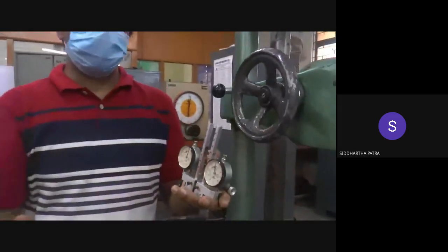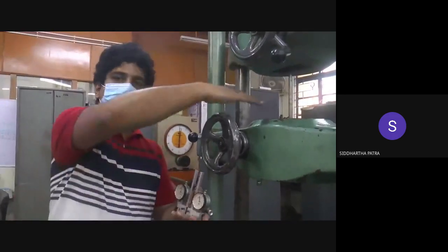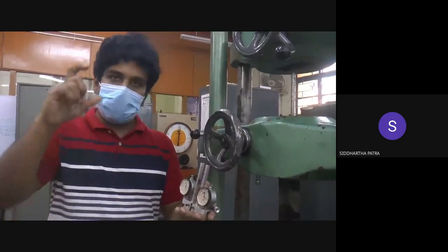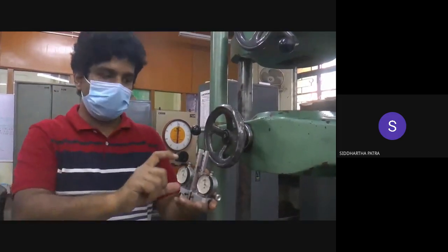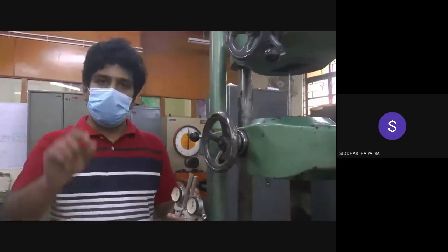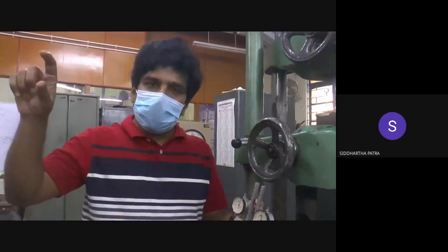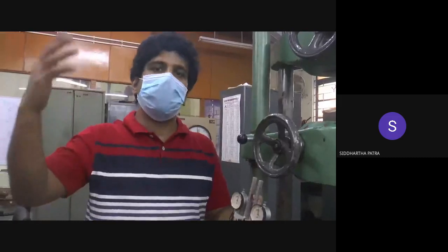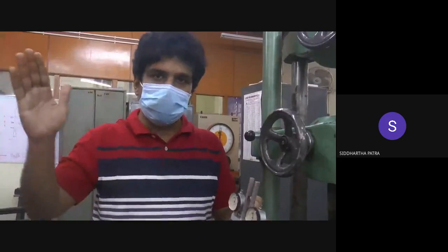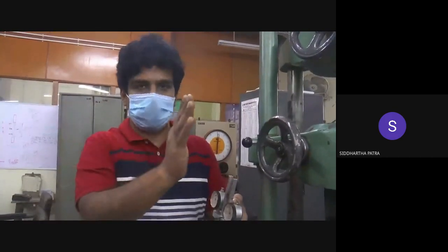Now I have mentioned three lengths. One is the total length of the specimen, that is about 350 millimeters. Then this effective length, which is the 10 millimeter diameter portion, and in that 10 millimeter diameter portion also, we are only taking a very small segment of 60 millimeters. The reason for doing that is that from the higher diameter, that is the 12 millimeter diameter portion, to the 10 millimeter diameter portion, there is a taper region, and in that the stress state becomes three-dimensional. It needs to have a smooth transition